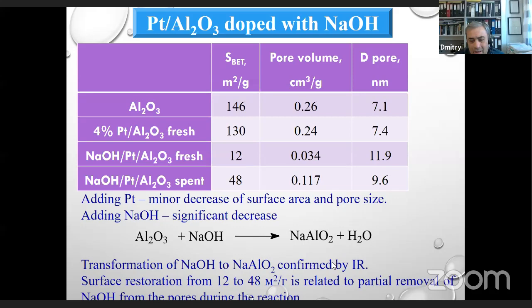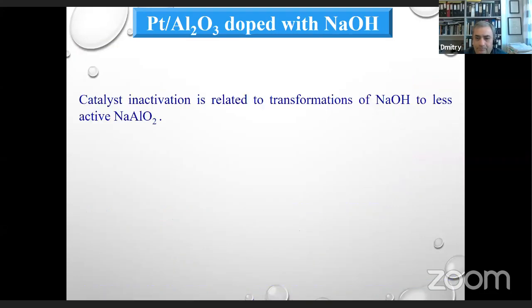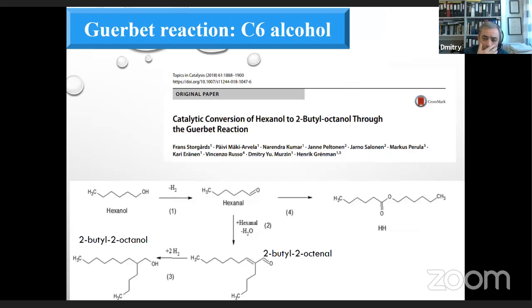And sodium aluminate apparently was or is not as efficient as sodium hydroxide for the reaction, not possessing the hydroxide group. So our conclusion was that the catalyst inactivation was related to transformations of sodium hydroxide to less active sodium aluminate, and also it's partially related to thermodynamic limitations, as I will explain after a while.